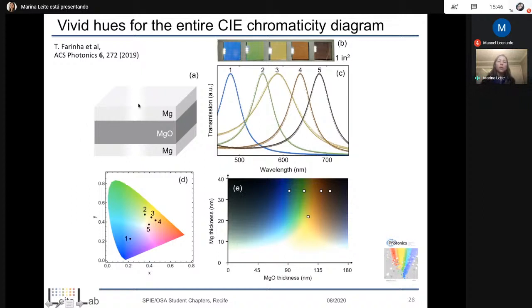What can we do? In this particular case, the optical device that we have is a stack of what we call an MIM, a metal, an insulator, and a metal. This MIM structure is a sandwich. You have MgO, magnesium oxide, in the middle, also biocompatible, also biodegradable, sandwiched by two layers of magnesium. So essentially we have a Fabry-Pérot resonance, a type of cavity. Depending on the thickness of this MgO, we can tune light transmission. If we make this MgO thickness smaller, we're going to have a blue shift.